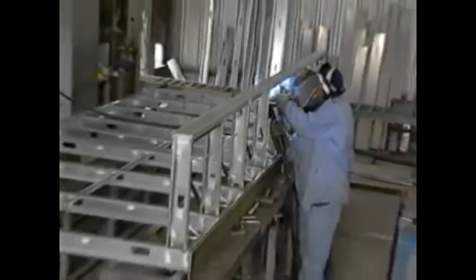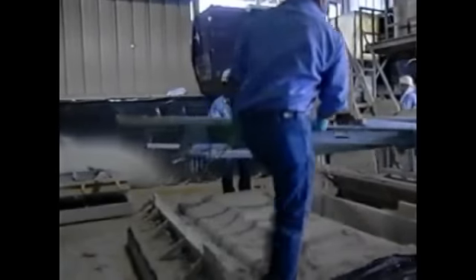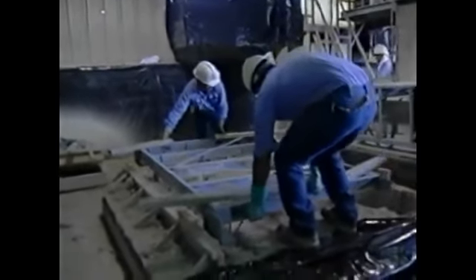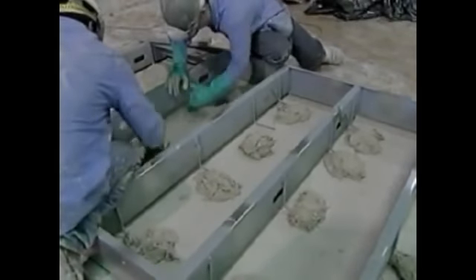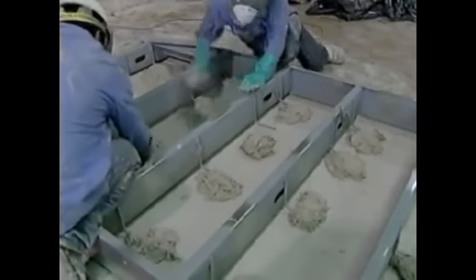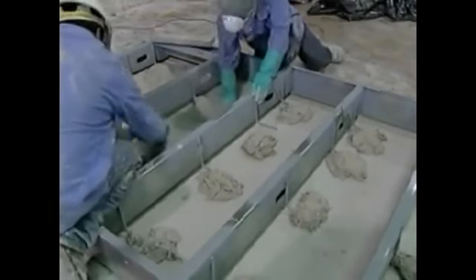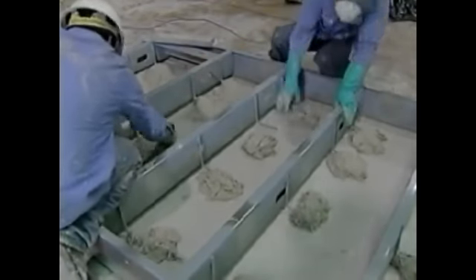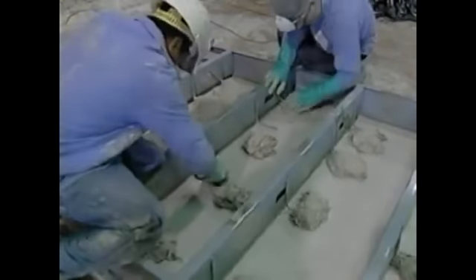Prior to the manufacturing of the panel, a frame of light-gauge steel stud or structural tube is welded. The frame is positioned over the GFRC skin as soon as the skin has been sprayed to the proper thickness. L-shaped flex anchors, pre-attached to the frame by welding, are attached to the skin with additional GFRC material known as bonding pads. The flex anchor enables the GFRC skin to move slightly to compensate for thermal and moisture movement of the GFRC face without undue restraint from the frame.